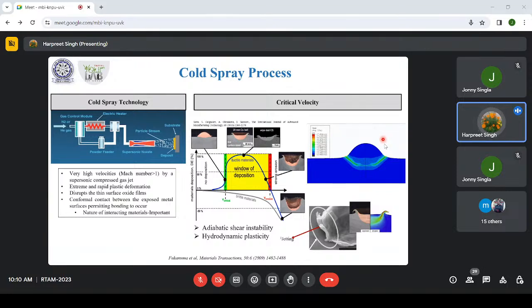This is a nice simulation done by my student, Vinay, who has shown us the single particle impact on the substrate here. You can very well see that the particle is coming and striking with enormous kinetic energy. The velocity is very high, so it's half mv squared. It will come and strike the surface, and there will be deposition, right? We are getting the deposition owing to this plastic deformation which is happening. In this simulation, both the substrate as well as the particle are deformable, so both are deforming. This is an ideal condition. Cold spray will be a very good option if both the materials are ductile, right?